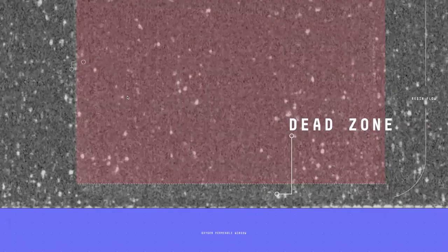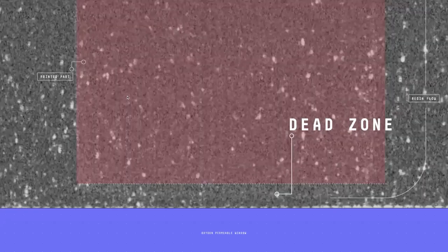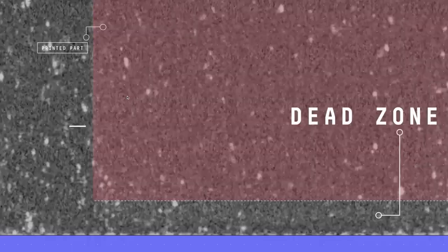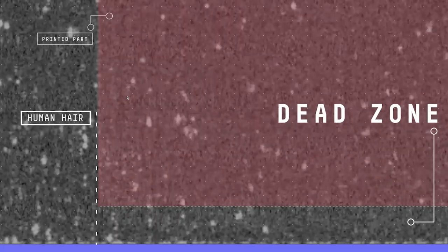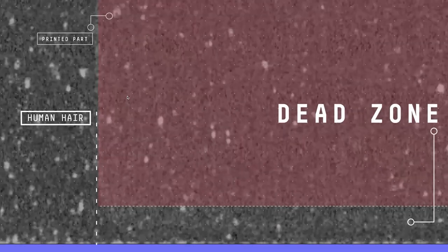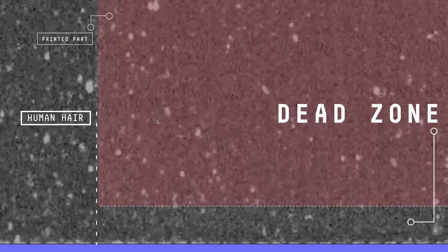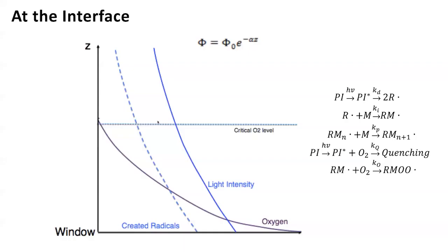And let me show you that. This is an optical coherence tomography image showing you the liquid being drawn in as a river as it runs into this part. And that liquid's got to get to the deepest pixel at any given cross section as the surface area is changing in contact with the window. So it's a mass transport issue. And we study this a lot. And so if you just look at this from a polymer chemistry, polymer physics point of view, what's happening here on the z-axis, we're going from the window surface up into the liquid. And this is a generic concentration axis where the window is here.